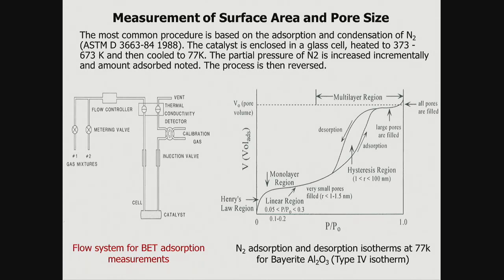Just increase the nitrogen, watch the adsorption as it goes up, the V for volume adsorbed on the left-hand side. As you increase the partial pressure across here, you're going up and you're following the arrow on the way up. The key thing here is that when you try to desorb it, it doesn't come back down the same axis. Now it could come down the same axis, and if it did, there'd be no hysteresis, which is what that region is called.